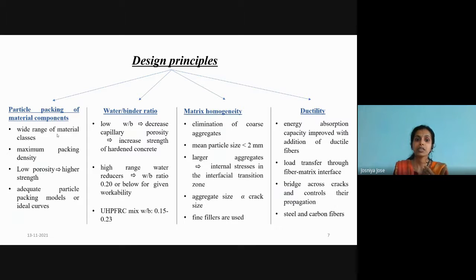And the second principle is the lower water binder ratio. We know that as the water binder ratio is decreased, the strength can be increased, and this is attained with sufficient workability with the help of high range water reducers. For a typical UHP-FRC mix, the water binder ratio ranges between 0.15 and 0.23. And the next point is the elimination of coarse aggregates in order to improve the homogeneity of the matrix. The particle size is less than 2 millimeter. The aggregate size is proportional to the crack size, so in this mix, fine fillers are used.